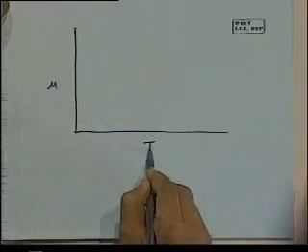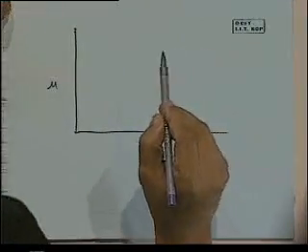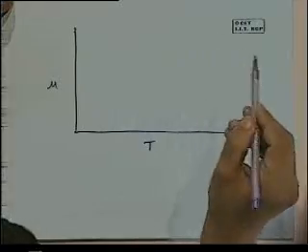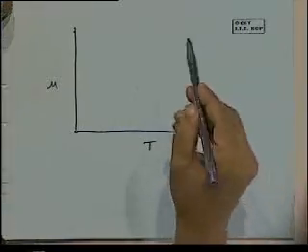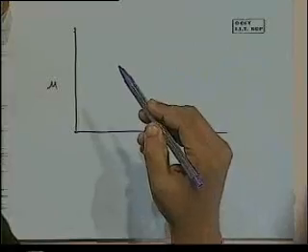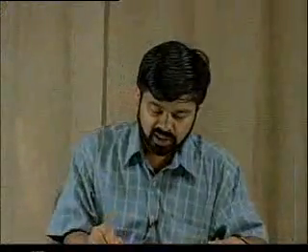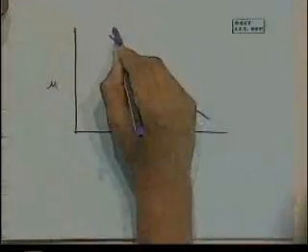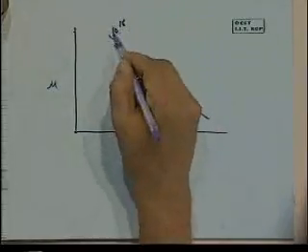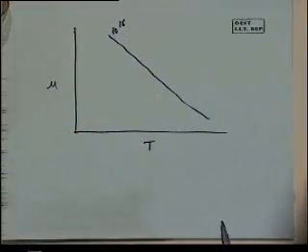Mobility has a temperature dependence, but there is also a dependence on the ionized impurity concentration. If we plot mobility versus temperature for the same semiconductor but with different amounts of doping, we're playing with how much ionized impurity scattering there is. At low concentrations — say silicon at 10 to the power 16 doping — we get one curve, and as we increase the concentration, the shape changes.